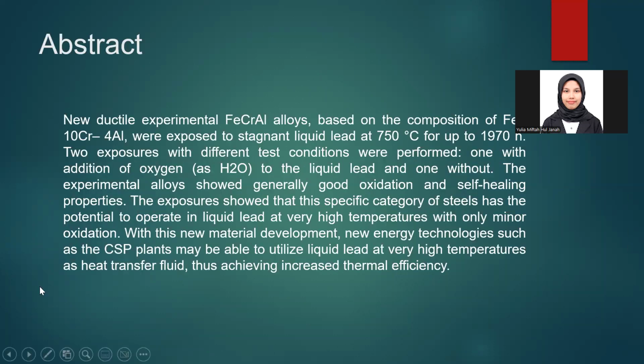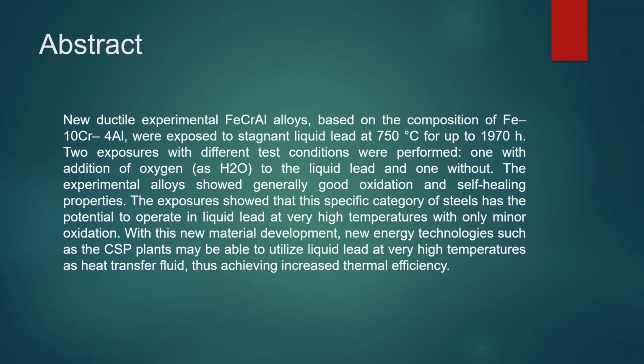For the abstract: new ductile experimental ferrochromium aluminum alloys, based on composition of ferro, 10% chromium, 4% aluminum, were exposed to stagnant liquid lead at 750 degrees Celsius for up to 1970 hours. Two exposures with different test conditions were used, one with addition of oxygen as H2O to liquid lead, and one without.